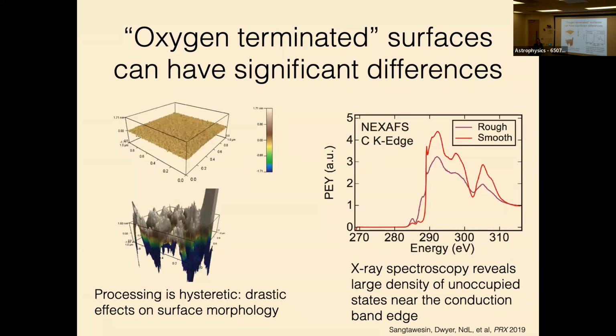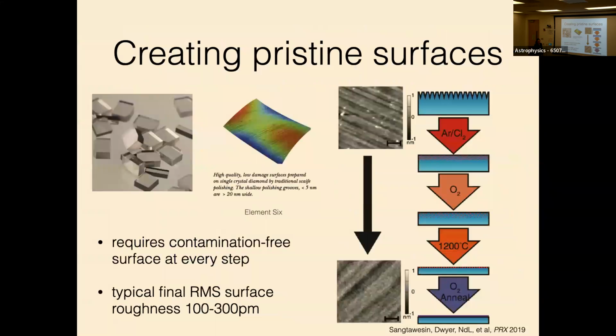So these are really natural candidates for this magnetic noise, because now I have a large number of electronic traps that can host charges transiently, which then lead to this noise. Okay, to spare you the really extremely long story about all of the different failure modes that we learned, the end result is that we now have this multi-stage process for creating very pristine oxygen terminated surfaces. We start with very smooth, low subsurface damage diamond that's polished in a particular way.